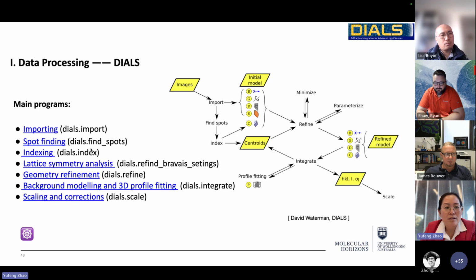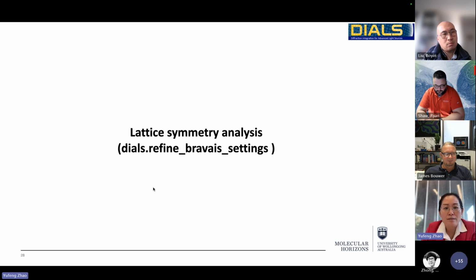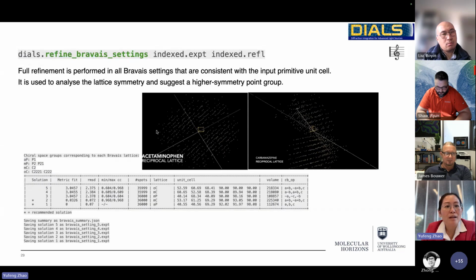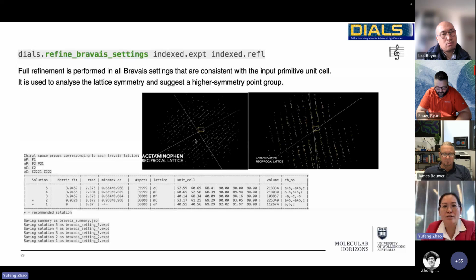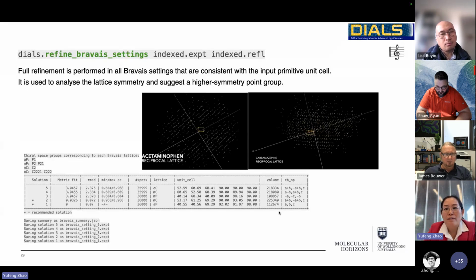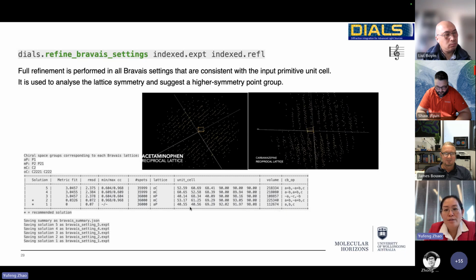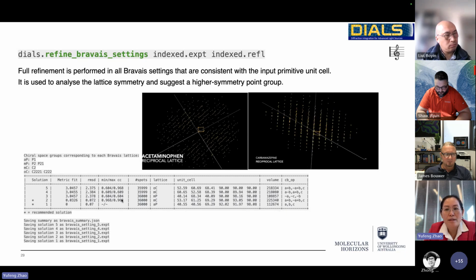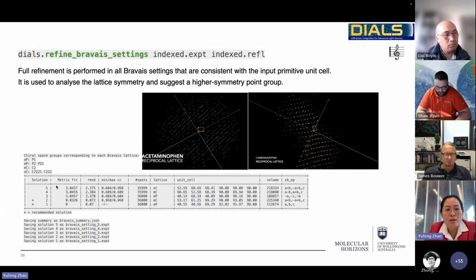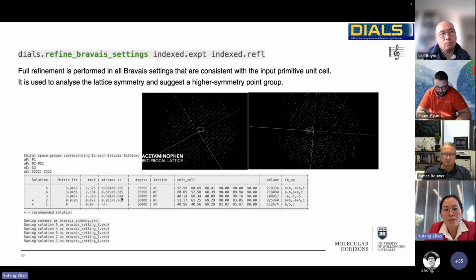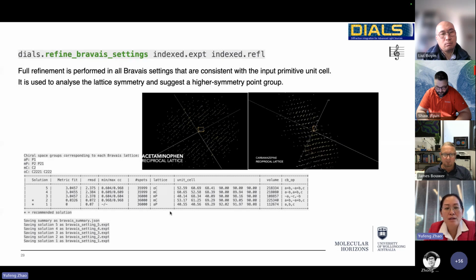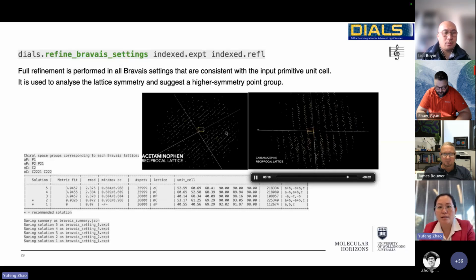So after the indexing, if you know your sample space group, you can use the space group to process. If not, we can try to do a symmetry analysis through the Bravais settings refinement program. This program performs a full refinement in all Bravais settings that are consistent with the input unit cell. It analyzes all the symmetry and normally gives a suggestion of a better, higher symmetry point group, with all the output metric fit, deviation, the correlation coefficient, and operation basis. And especially, I think the good thing about DIALS we like is this Bravais settings viewer. We can see the unit cell directly.